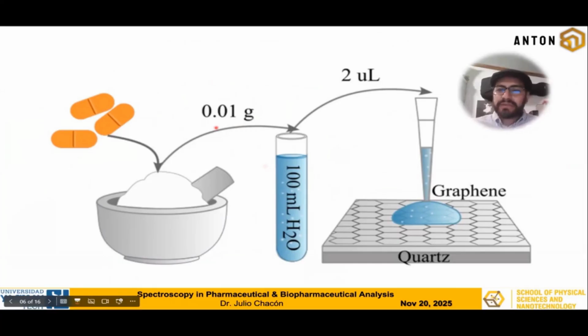So we took 0.01 grams of the pharmaceutical, we put it into 100 milliliters of water, and then we extracted only 2 microliters of that and made a tiny drop onto graphene on quartz, standard graphene on quartz. We did that in order to determine if there was some interaction between the pharmaceutical molecules, the structure of the molecule, and the graphene surface. And that was extremely interesting because what we found is that indeed the pharmaceutical makes a supramolecular interaction that connects with the graphene and then enhances the signal of graphene, and lets us observe the fingerprint of our pharmaceutical molecule.